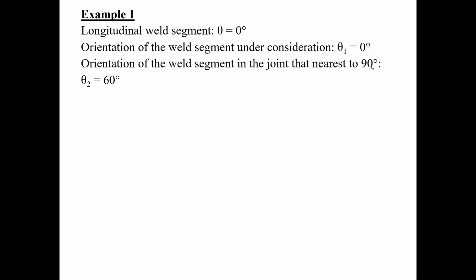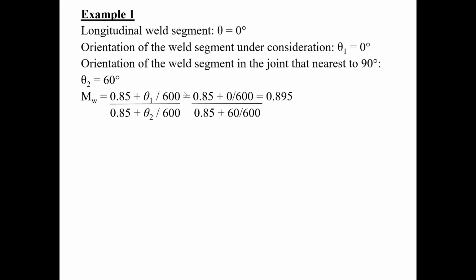Theta 2 always stays 60 degrees. Now the Mw is going to change. So for those two segments, the Mw drops down to 0.895 because this here is 0 degrees. Theta 2 stays the same for all. Once you determine which weld segment is nearest to 90 degrees, that always stays theta 2. So when I'm calculating the resistance of those two welds, I'm going to have to multiply the value of those two by 0.895 in the equation.